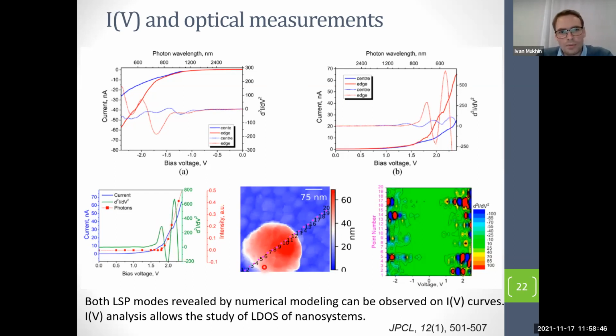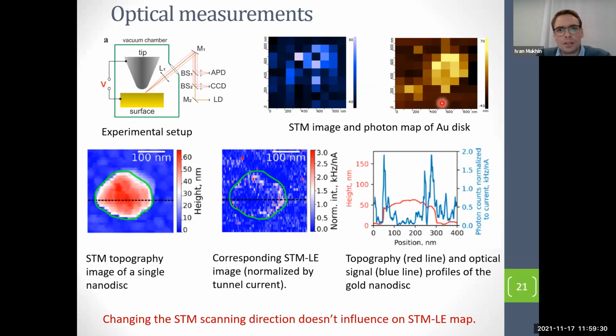And actually, we have performed an IV curve study across the diameter of the nanostructure. This is the fingerprint of these IV curves, with the position here showing the position of the nanotip. I don't want to discuss it in detail, but all the peaks which can be seen on these fingerprints correspond to features in the IV signal which correspond to features of the local density of optical states of the nano-antenna. So these results show that we can improve the efficiency of light emission if we use a plasmonic structure, and it's a very important way to position your tunnel contact so that you can also increase the efficiency of emission.